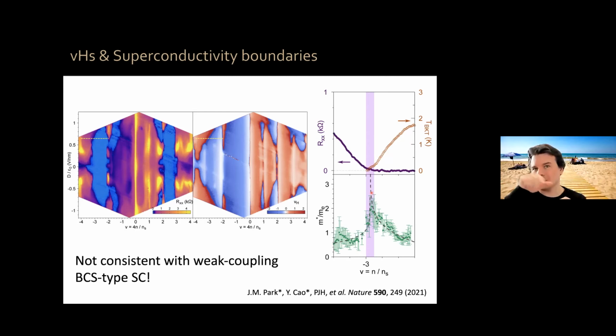However, in this system, as we change the filling factor, as the density of states increases, the critical temperature decreases rather than increases. And moreover, at the Van Hove singularity, the critical temperature becomes 0. Superconductivity ends at the Van Hove singularity instead of being maximum and strongest there. So this is something which is very unusual.